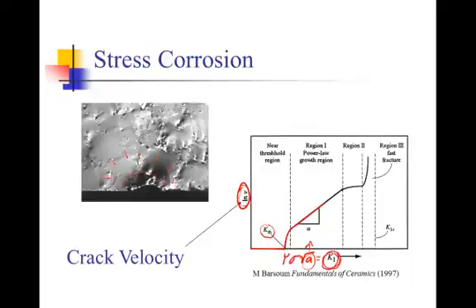And this continues to occur until the crack is growing fast enough that the moisture can no longer diffuse to the tip of the crack, and that causes the rate of crack growth to level off at this point where there's a short plateau. And then we reach the critical stress intensity factor, the fracture toughness, at which moisture is no longer necessary to catalyze crack growth, and the crack takes off very rapidly and within a fraction of a second breaks through the rest of the ceramic component.